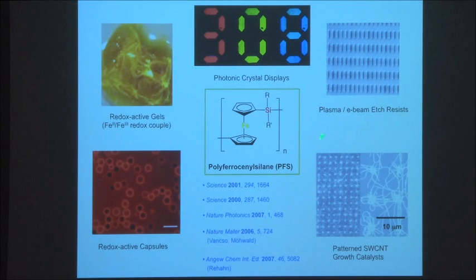You can heat the patterns up and turn them into magnetic materials, so you can pattern the polymer and then heat it up to create iron nanoparticles, which in the presence of a hydrocarbon gas mixture will generate single-wall carbon nanotubes. And these are very well-defined carbon nanotubes that you can make by this method. And they've been used by other groups in devices, for example.